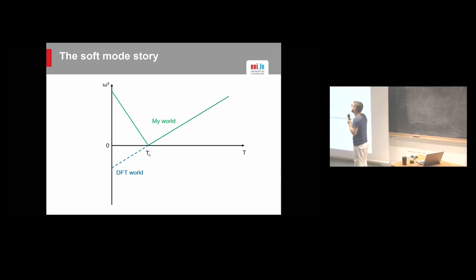Now, of course, I live in a world where frequencies don't get negative. So what happens is that this works well, but then what happens here is that you switch to the low symmetry phase. So the phonon frequency renormalizes here and goes up again. Okay, so this is what you expect in real life. So this would be the para phase, and this would be the ferroic phase. It doesn't have to be ferroelectric; it can also be ferroelastic.